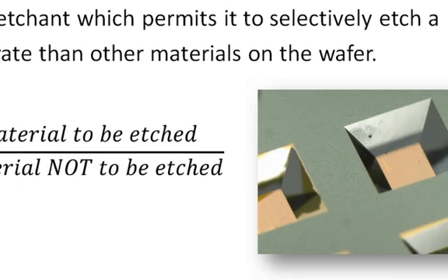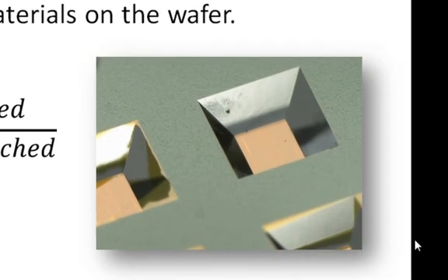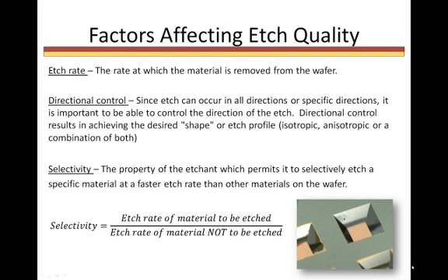For example, if we refer back to the backside etch for the MEMS pressure sensor, which we talked about in part 1 of this series, we need to use a mask that can withstand the wet potassium hydroxide etch, which can last up to 4 hours. This process has to etch all the way through the silicon. Therefore, we want the masking layer to be basically non-reactive with KOH, or potassium hydroxide, or to have a very, very low etch rate relative to the etch rate of silicon.